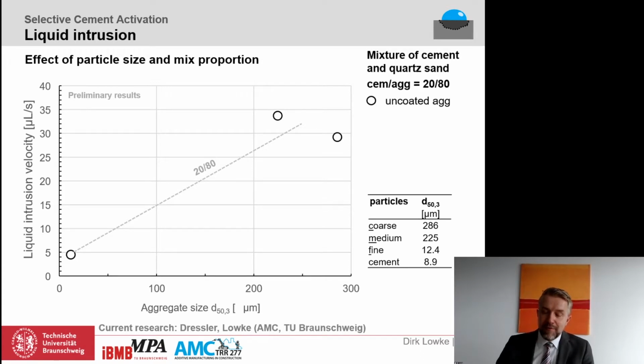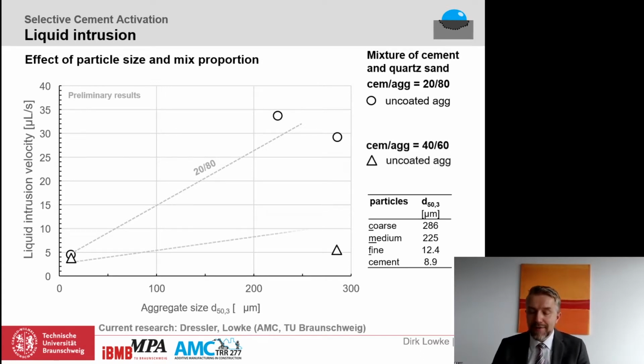In the second step, we varied the ratio of cement to aggregate from 20 volume percent cement and 80 volume percent aggregate to a ratio of 40/60. And you can see with increasing cement content, the intrusion velocity significantly decreases. This concrete technology variation corresponds to what we actually expected. However, the variation of cement content and particle size is not always an option. So we are looking for further ways to control the penetration behavior.